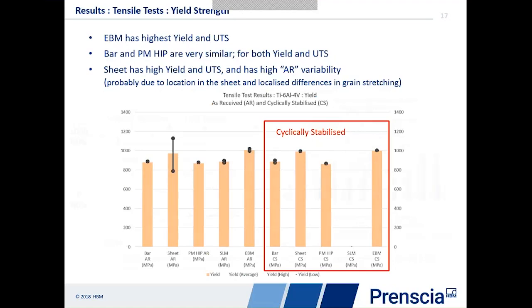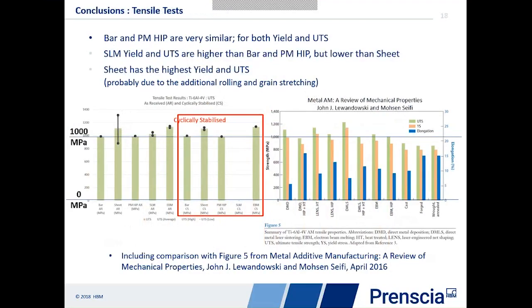And going further, if we go beyond tests that we've done in our labs, then I can show you here some tests that have been done in a publication. So you can find this on the internet or in a paper. And again, this one shows us the different sort of expected tensile properties across a whole range of the same material under different conditions. And we see that what we're finding here is consistent results. So when it comes to tensile properties, the additive manufacturing are pretty much in the ballpark of what we expect from the wrought materials. Tensile properties don't seem to be affected significantly.